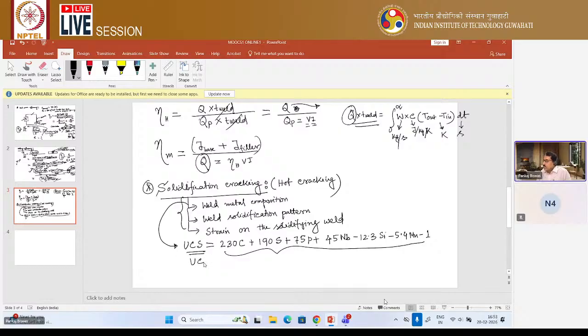Now, based on this UCS value, one thing you should keep in mind: in case of butt welds, if this UCS value is less than 25, then your weld metal is quite free from solidification cracking. This you should keep in mind.